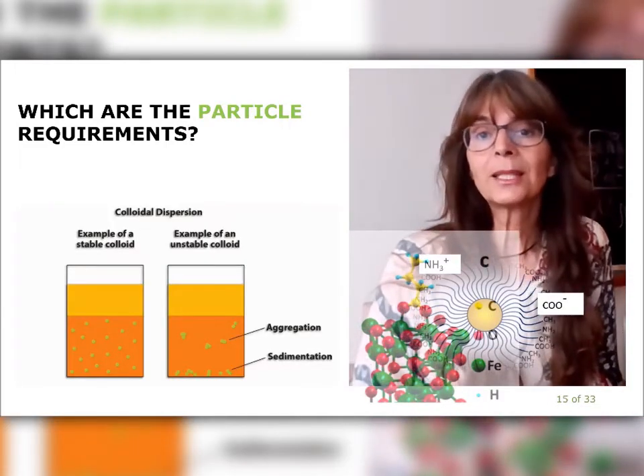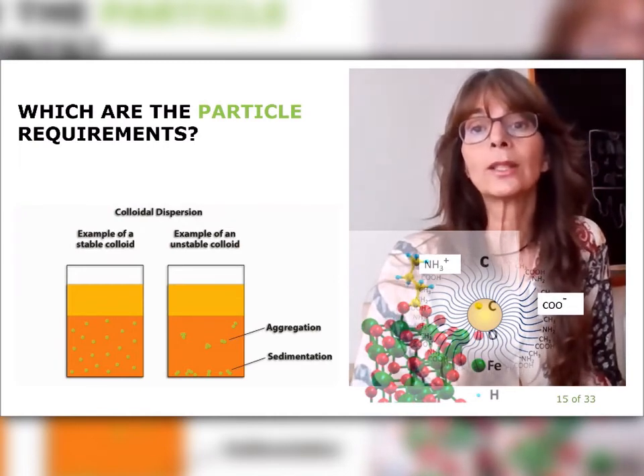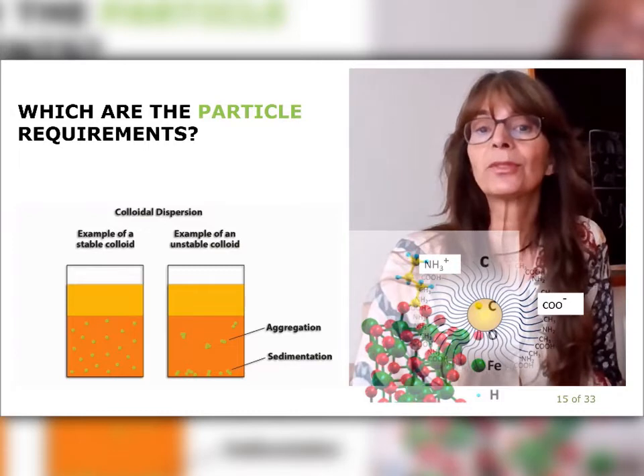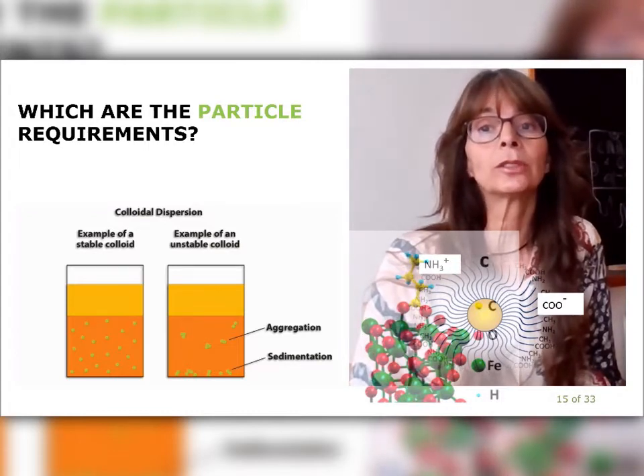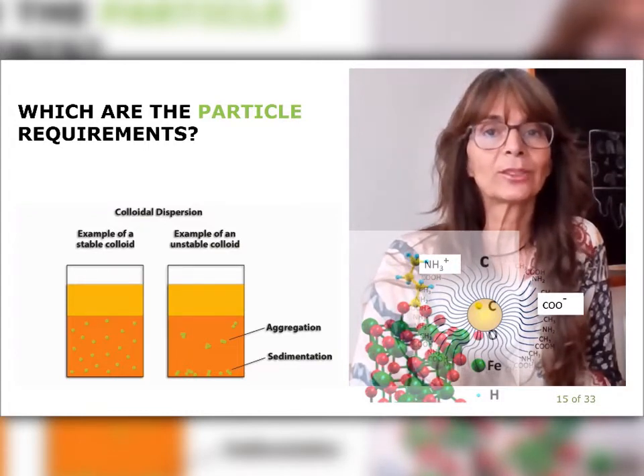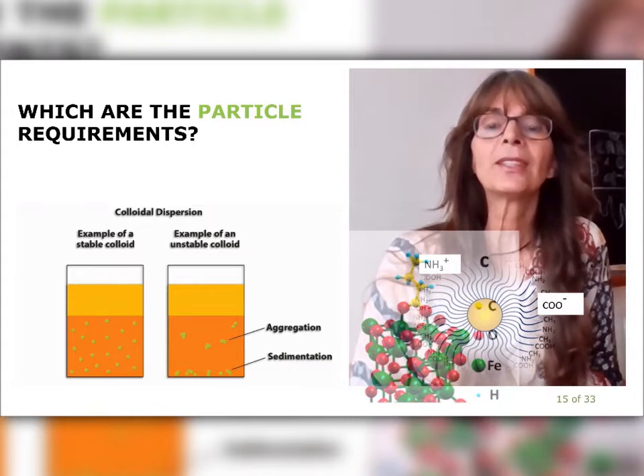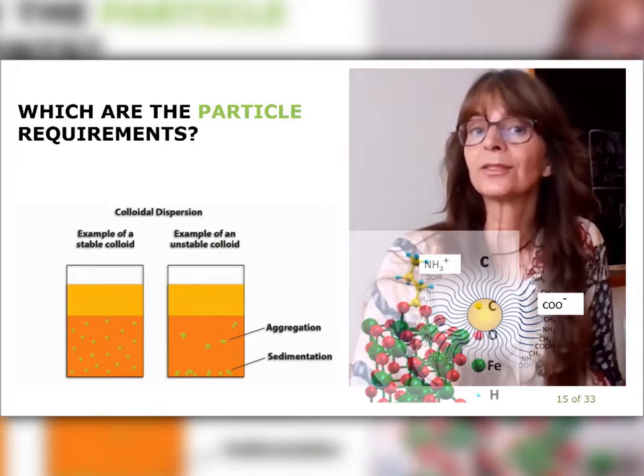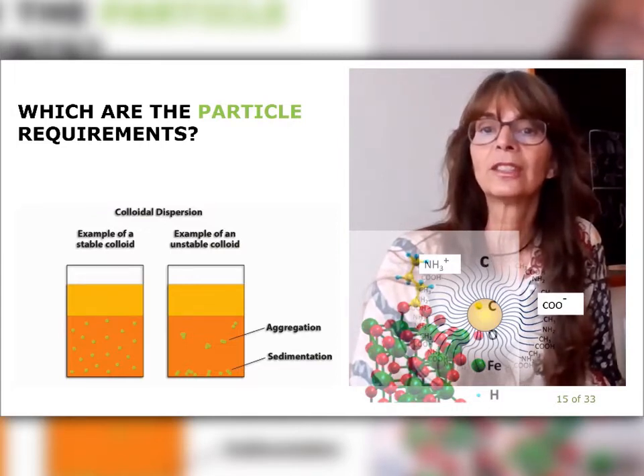And the particle coating also contributes to the colloidal stability. The chemical group endings provide electrostatic repulsion to counteract the van der Waals attraction. But for this, it is also crucial that the particles do not have a permanent magnetization.